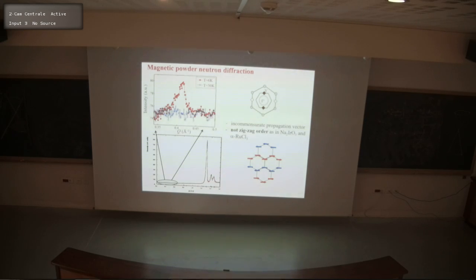So to find out more about the microscopic ordering, we do powder neutron diffraction, and that's, as Colin explained, neutron diffraction observes the magnetic periodicity of the order via the interference Bragg scattering. And this is the plot of the diffraction pattern. All of these strong peaks correspond to the crystal structure, neutron scattering from the nuclei. But down here, if we zoom out, there is a new peak that appears at low temperatures, and this is associated with magnetic ordering. And what was surprising when we did these experiments was that this magnetic wave vector, of course, we can only know the magnitude through these measurements.